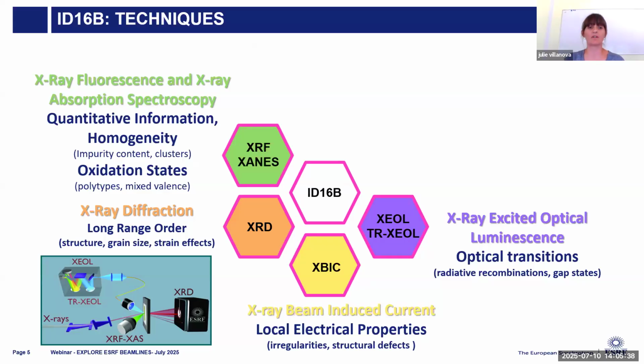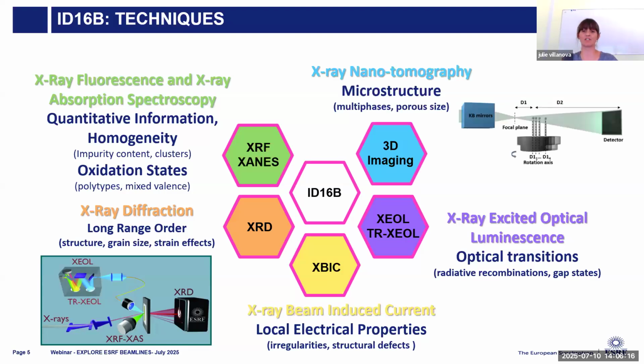Starting with the scanning techniques, we have X-ray fluorescence to get chemical information in the sample. While also scanning the energy around the K edge or L edge of a chemical element, we can perform XANES. We are equipped to also register the diffraction for the crystallographic phases in the sample, but also to look, thanks to XBIC, at the local electrical properties, and using XEOL and time-resolved XEOL, at the optical transitions. The second group is in fact only one technique, a full field technique, where instead of using the focused beam directly, we use it as a secondary source, and then use the conic beam to perform X-ray nanotomography to retrieve the 3D internal microstructure of the samples.